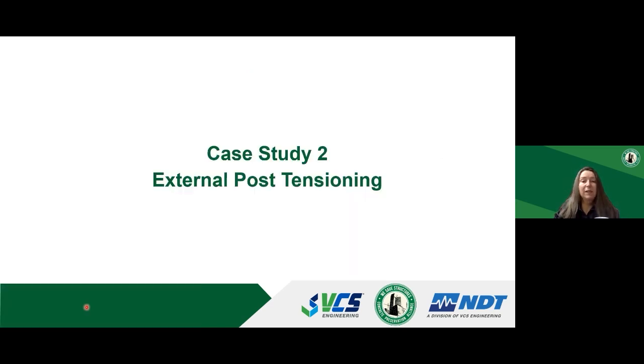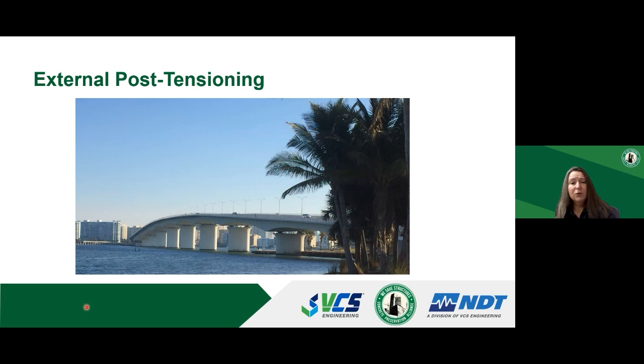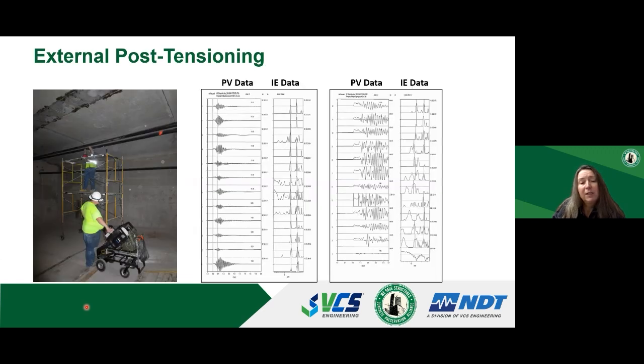Next. Okay, our second case study is going to look at testing of external post-tensioning. This is Ringling Bridge in Florida that uses external post-tensioning inside the girders. The investigation for this bridge was initiated by a tendon failure. So the photo on the left shows the impact echo testing of external tendons. And the image in the middle of the slide shows the impact echo and pulse velocity data that was collected on a fully grouted tendon.